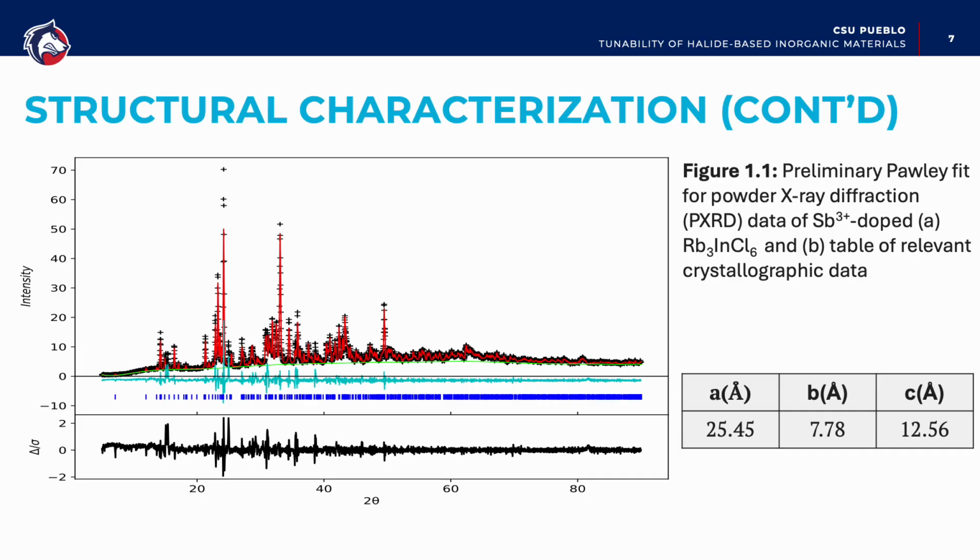However, we believe this had something to do with unideal experimental conditions with our microwave synthesis, meaning that there may have been some hydrated phase contamination somewhere in the lattice, but that's yet to be determined with some further experimentation. And you can see here that the unit cell parameters closely match the previously reported data.